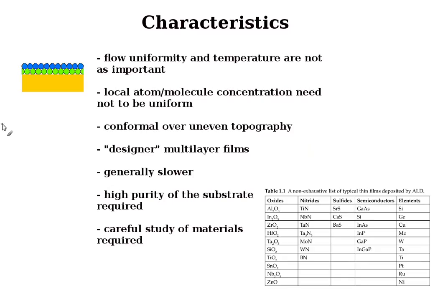Now let's talk about characteristics of atomic layer deposition. So, flow uniformity and temperature are not as important for ALD as they were important for CVD, because the process is self-limiting, but the temperature should fit into a specific range for this process to work. Local atom molecule concentration doesn't need to be uniform, provided that flow of the material is strong enough. This process is extremely conformal over uneven topography. And of course, you can create designer multi-layer films by depositing various materials in the order that you want,